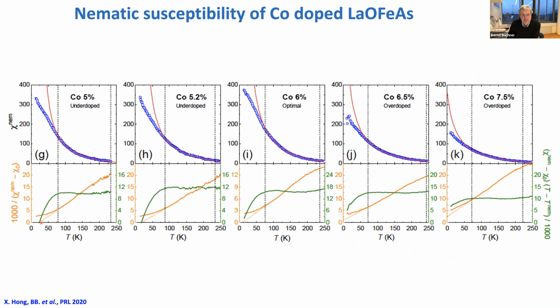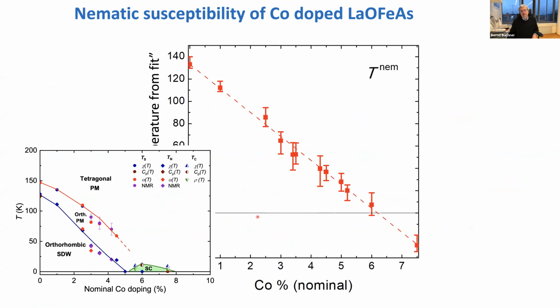And when you just look at the Curie-Weiss temperatures, you see that it first is positive and it crosses zero just at optimal doping. So this is the best superconductor which we have in these systems. And then it becomes negative for the overdoped compound. So it's very easy to identify the optimal doping here from the normal state strain derivative of the resistivity. So this is the corresponding diagram of this nematic susceptibility, so this characteristic temperature, this Curie-Weiss temperature as a function of doping. You see the crossing here at 6%, it's just there where we have optimal doping. So in some sense, you continue this line here, though the structure phase transition or the real 3D order disappears. Just looking at the characteristic energy scale, we follow this line and it hits exactly the zero for optimal doping.